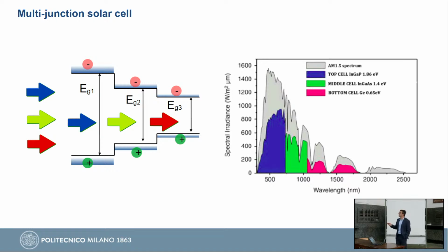These solar cells are putting together 3-5 semiconductors with different band gaps. So you start with one with a wider gap, which takes, let's say, the visible part of light at shorter wavelength, but it cannot absorb the one at longer wavelength, the yellow one. Then you put another semiconductor with a smaller band gap, which will take this part, and then another one which takes the infrared part. In this way, you generate electron-hole pairs, which can be collected